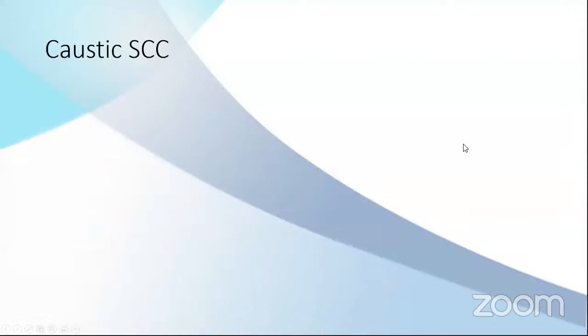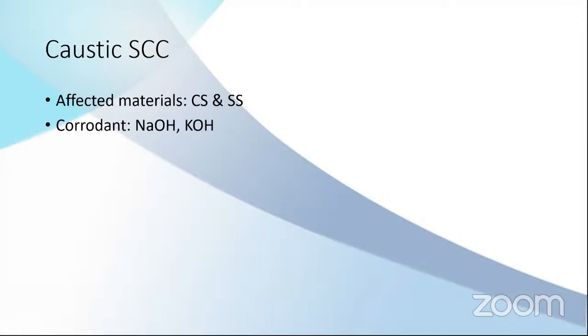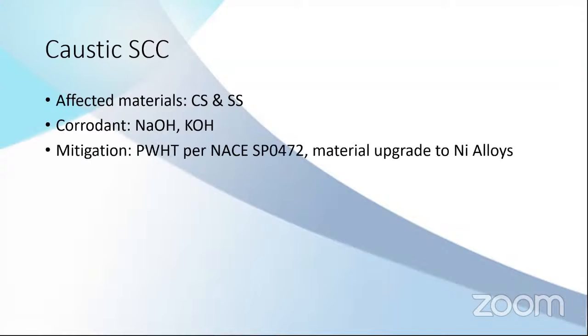Caustic stress corrosion cracking. Affecting materials, carbon steel and stainless steel, they are both susceptible to these cracks. The corrosion are caustic, NaOH or KOH, natrium hydroxide or kalium hydroxide. This also happen mostly in caustic plant or refinery because they were both using caustic quite a lot.